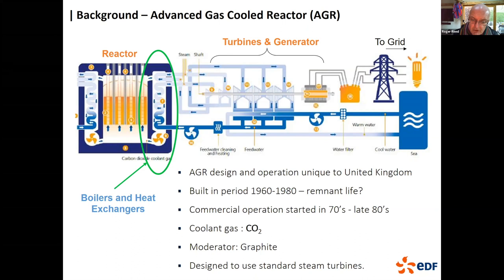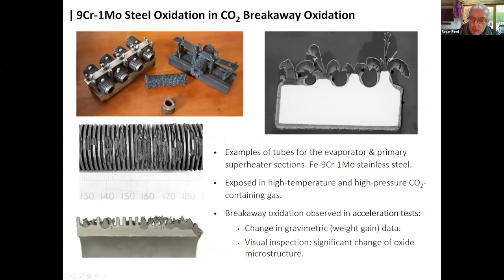Now, these reactors are quite unique in a number of ways, but in particular because of the use of coolant gas, which is CO2. And so this, of course, gives some challenges for the corrosion of the boilers and the heat exchangers in this part of the plant. If you look at the way in which the tubes behave in service, not anticipated was the possibility of this so-called breakaway oxidation in the high-pressure CO2, which is on the active side of the barrier here. Of course, one needs to have these steels to conduct heat so that one can heat steam on the inside of the pipes, because those then go off to the steam turbine where the power is generated.